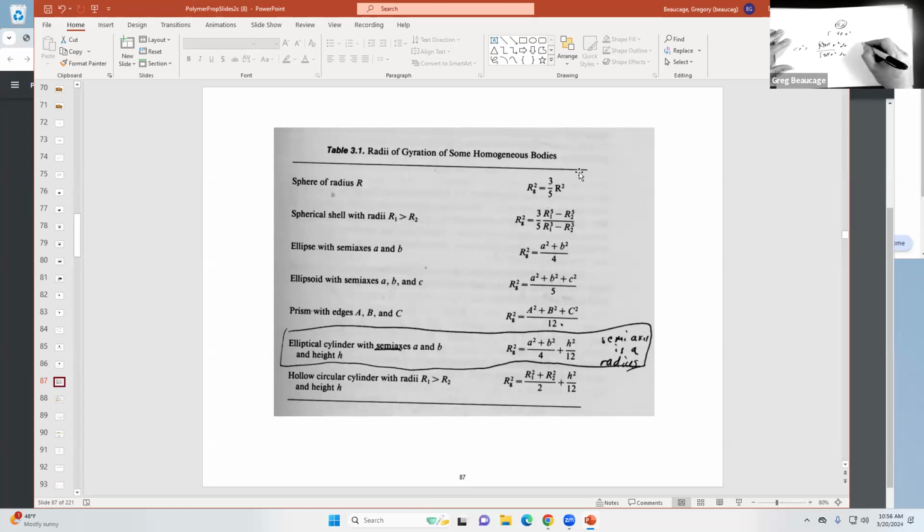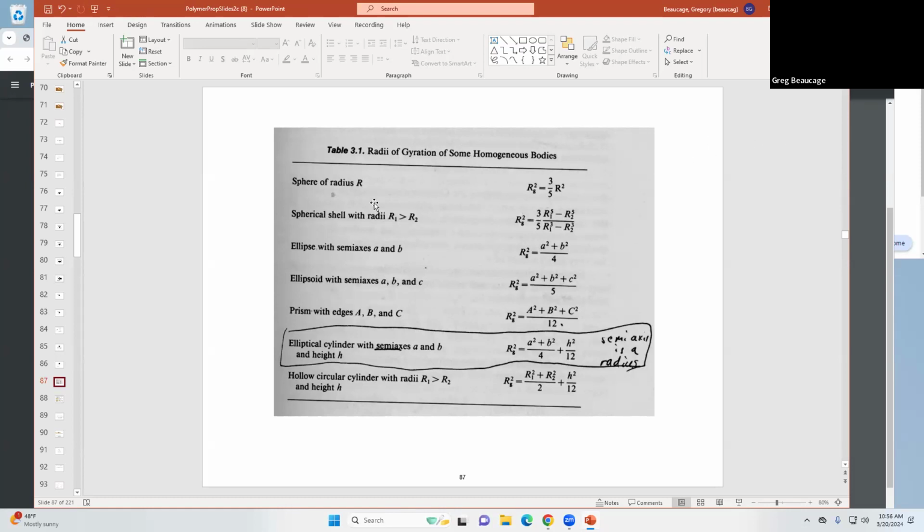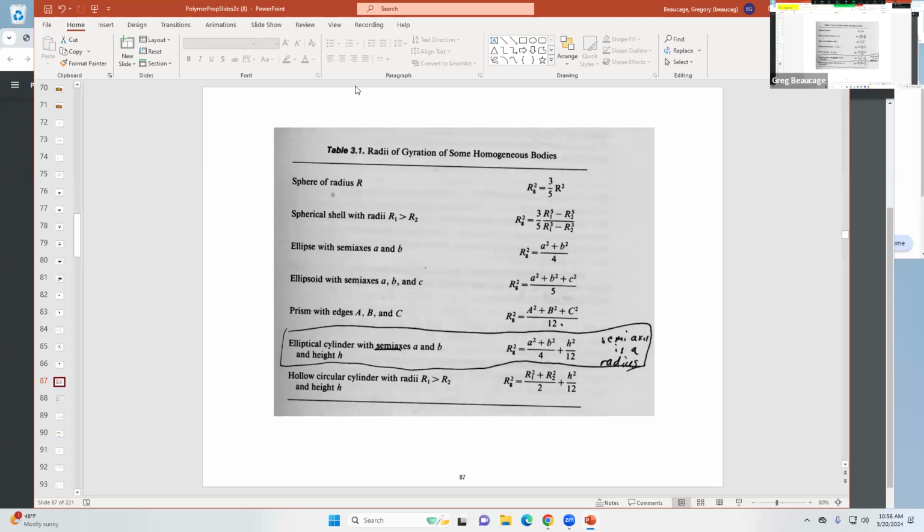This is r to the 4, that gives you r to the 5 by 5. And this is r cubed by 3. So you get this 3/5. So Rg squared is 3/5 of the integrals, 0 to r, of the radius of the sphere squared. So 3/5 r squared is the sphere one. And you can do the same thing for any kind of simple shape you can think of. It's kind of a list of Rgs you can get.